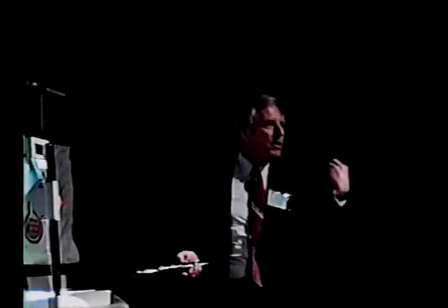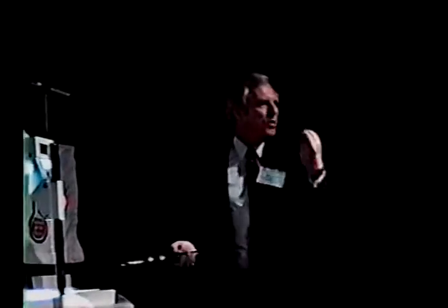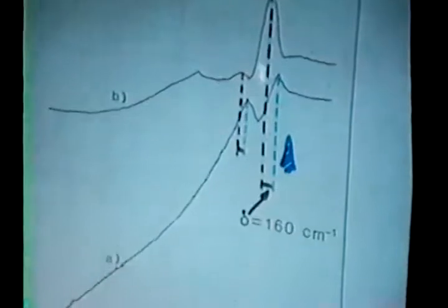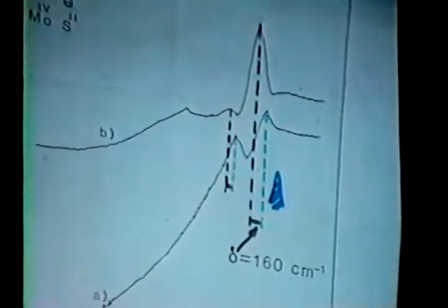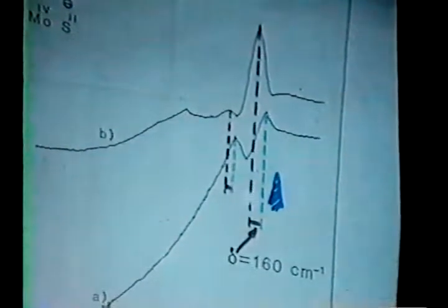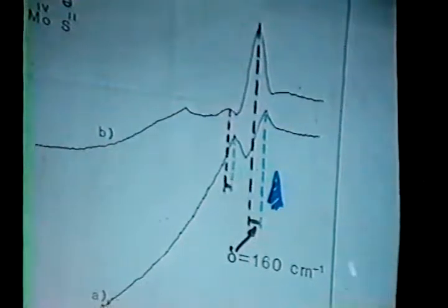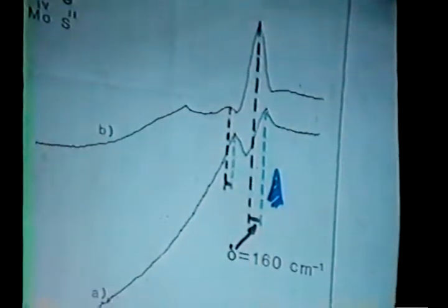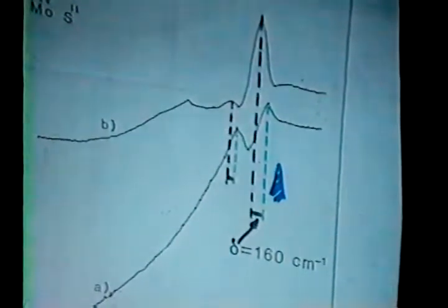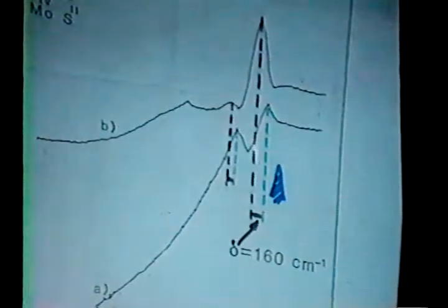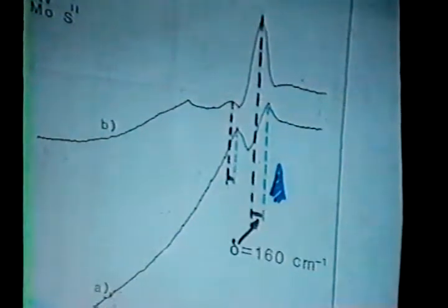They are partially occupied with electrons and still to major part empty. They're not altered much because these shifts here, which would indicate how these states are altered, are only of the order of 160 wave numbers, which is 2 × 10⁻² electron volts. Incidentally, optical spectroscopy has that resolution. And you would not see this kind of shift by any electron spectroscopy that is available today.